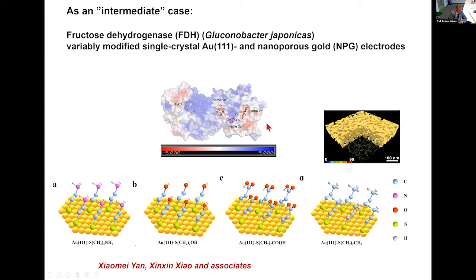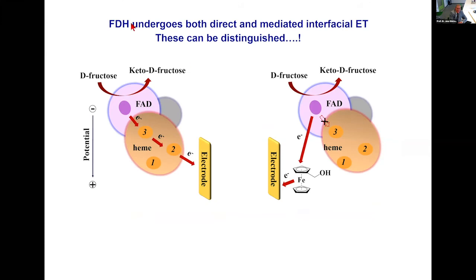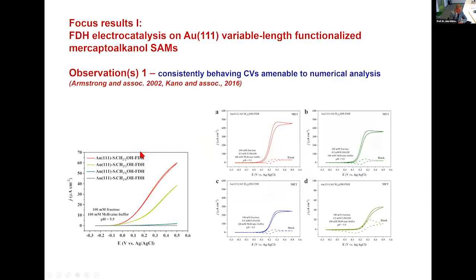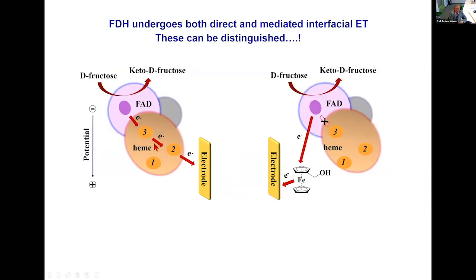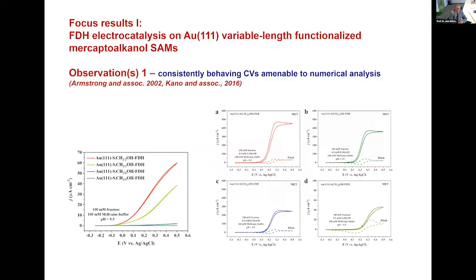This is the target molecule, target enzyme, fructose dehydrogenase. It contains a catalytic center, FAD center, and then an electron transport channel via 2 heme groups. It can transfer electrons either directly or via a mediator here, ferrocene. And there are ways of calculating how large a fraction of the total active enzyme on the surface transfers electrons directly and how much by mediation.